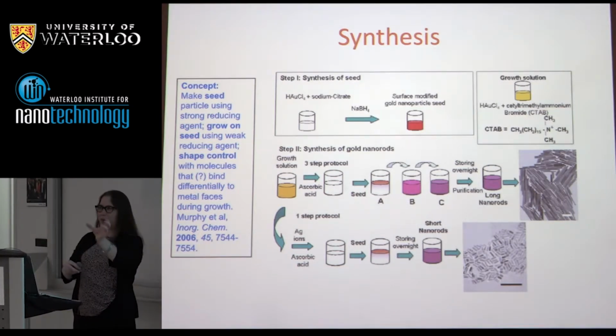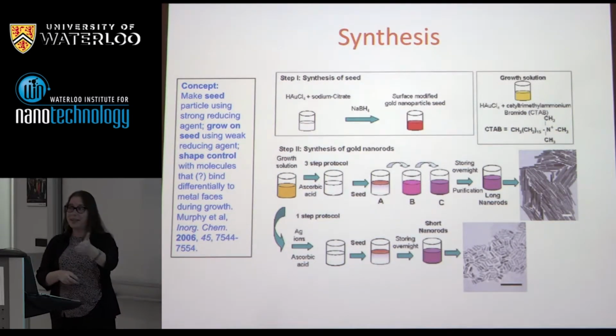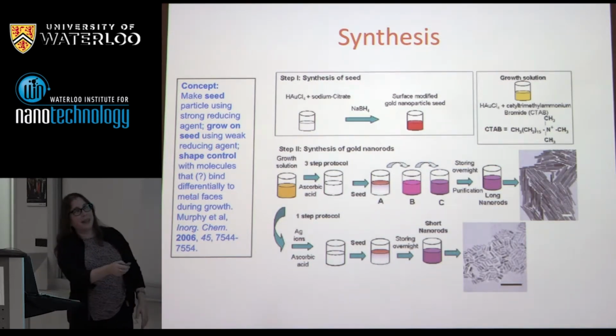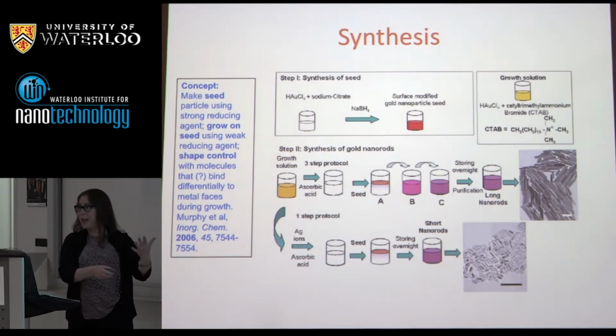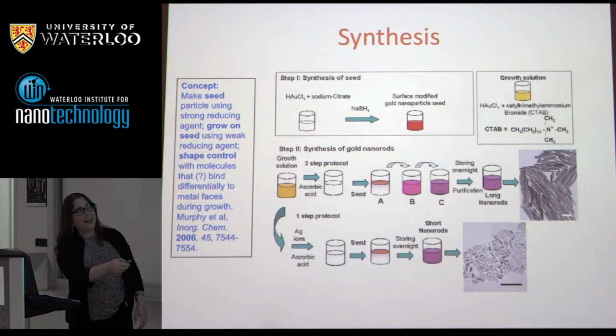We have our soft rod-shaped thing in solution. Our seeds assemble in some electrostatic fashion, and then we pack together a polycrystalline rod. Now that's not what happens, but that's why we picked this stuff, and it actually does produce rods. Anyway, so in early days we did the following. Here's my metal salt with this CTAB stuff. I add my weak reducing agent first, because it turns out order of addition matters here, which is telling you things are very kinetically controlled. And then I add my seeds last.